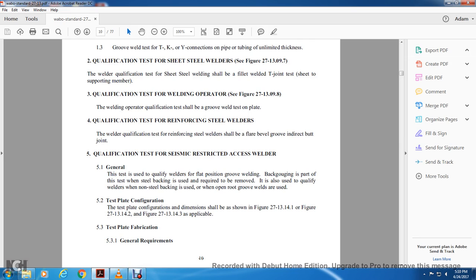5. Qualification testing for seismic restricted access welders. General: this test is used to qualify welders for flat position groove welding, with gouging and back gouging as part of the test, and steel backing used with the wire to be removed. If used to qualify welders for non-steel backing, an open root with groove welds is used. Test plate configuration dimensions shall be shown in figure 2713.14.1, figure 2713.14.2, and figure 2713.14.3, as applicable.